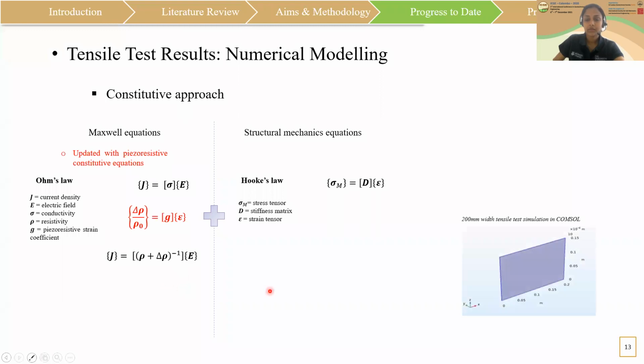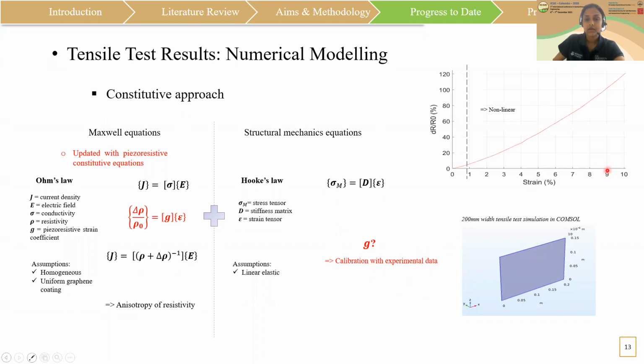A computational model was initiated in the COMSOL Multiphysics platform, assuming the material to be homogeneous and the graphene coating to be uniform. And the anisotropy of resistivity was also accounted for in the G matrix. Linear elastic conditions were assumed for the mechanical model, and the model was calibrated using the experimental data to find G. Also, strain-dependent piezoresistive coefficients are to be found to capture the non-linearity in the electrical response of the material.